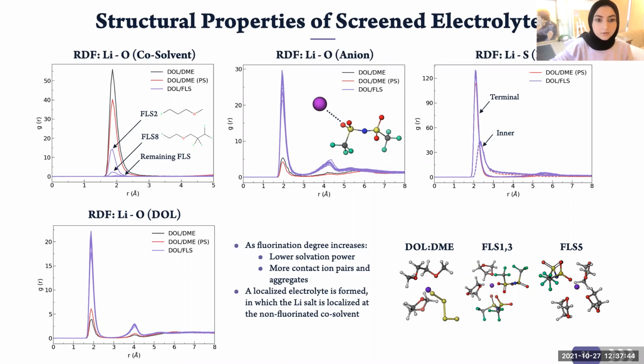For the coordination between the cation and the anion, we can see that there is a much stronger interaction with the anion in the fluorinated systems compared to the conventional electrolyte solution. And this can be an indication of the presence of contact ion pairs in the solution or even aggregates. And this is, of course, not desirable because it can lead to reduced diffusion coefficients and dynamical properties in the solution. And there are also more long-range interactions with the cation here. For the coordination of the cation with the polysulfide, if we look more closely, we can see that there is stronger interaction in the fluorinated system than in the conventional electrolyte. And this behavior will be explained in more detail later.